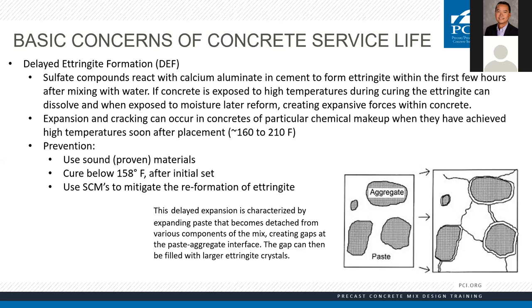PCI has requirements for limits on your curing — you can't ramp up your heat faster than a certain amount and can't exceed a certain temperature. ACI limits that to 160°F. PCI says for a straight mix design, your internal concrete temperature should not exceed 158°F — and notice that's internal concrete temperature, not the heat of the steam around your piece. If you use an SCM like slag or fly ash, ACI says you can go up to 210°F internal concrete temperature, because those SCMs mitigate delayed ettringite formation.